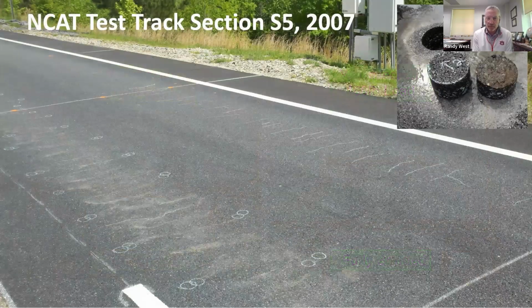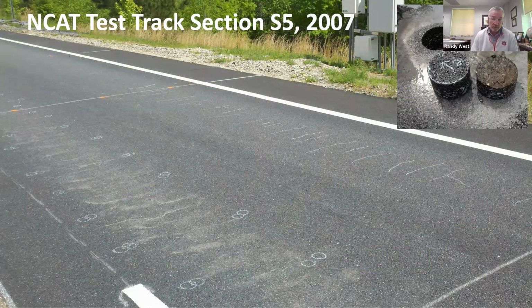As Nathan mentioned, we've had occasion to observe this on the test track. Back in 2007, we had section S5 that had fatigue cracking, and you see the little picture in the inset there showing a core taken out of that section, and it came out with a debonded interface between the base and the intermediate layer.